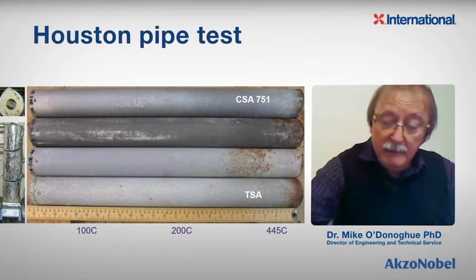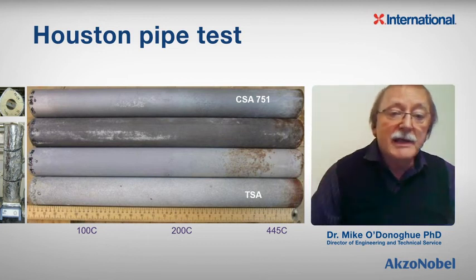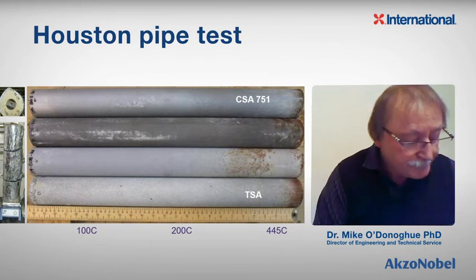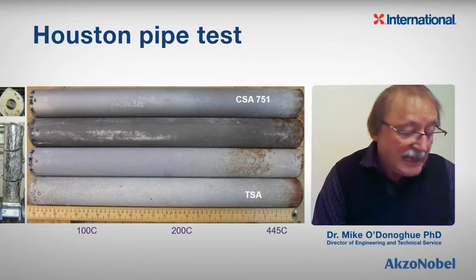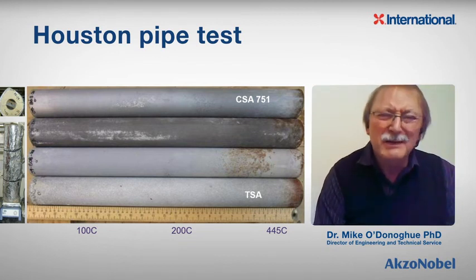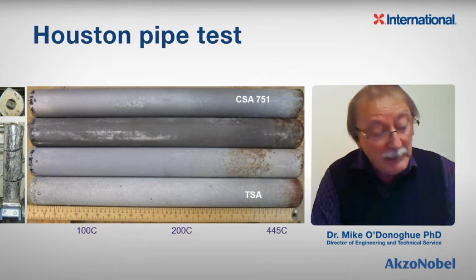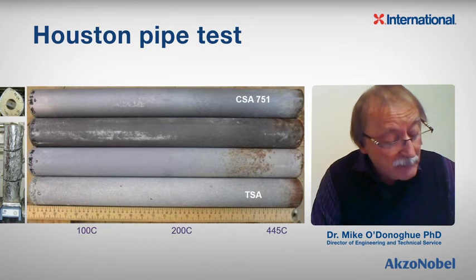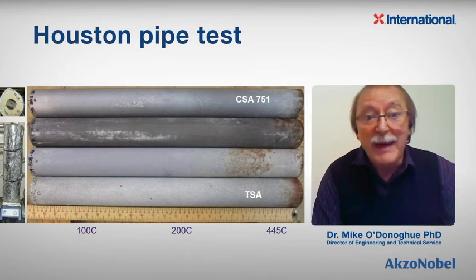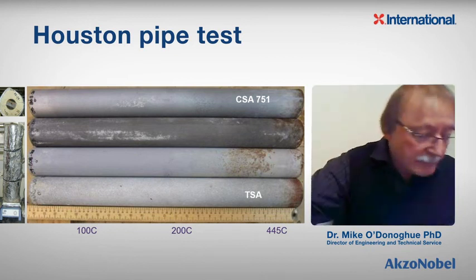Now what this is, large piece of this, like you see, abrasive blasted the pipe, carbon steel. And as I said, we have done stainless. And we coat it. And then we insulate it. From the top, you'll see it's insulated with CalSil. Well, why do we use that, not perlite or something? Well, because CalSil will absorb moisture like crazy, 20, 30 times its own weight. So we want it to be bad. We want to set up bad conditions and see how well these things work.